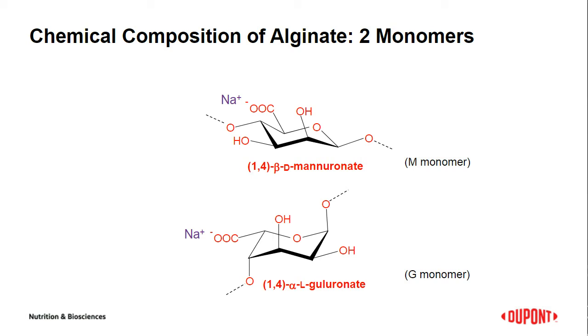It is important to note that the shape of the M versus G blocks differs from one another. M blocks are formed from equatorial groups at C1 and C4, which leads to a straight polymer with a flat ribbon-like structure. However, the G blocks have axial groups at both C1 and C4, resulting in a buckled chain. This buckled chain is of high importance for the gel formation and the interaction with the calcium ion.